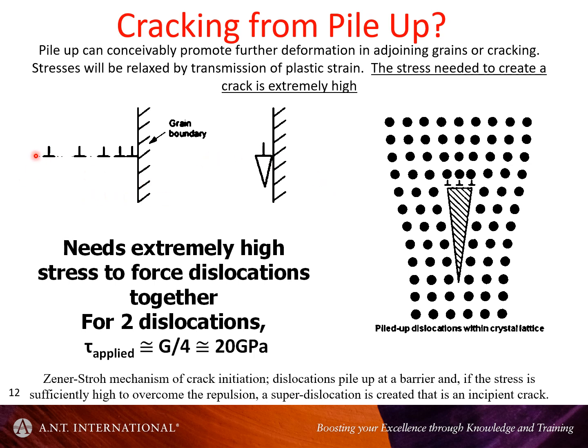So the idea is that if you have enough dislocations in the lock, in the slip band and against a lock, and the applied stress is sufficiently high that let's say it's 10 times the lattice friction stress, it is possible then to force dislocations together and create, on a microscopic scale, a crack. But even for two dislocations, the applied stress at this point has to be extremely high. 20 gigapascals is roughly what one would expect for two edge dislocations.